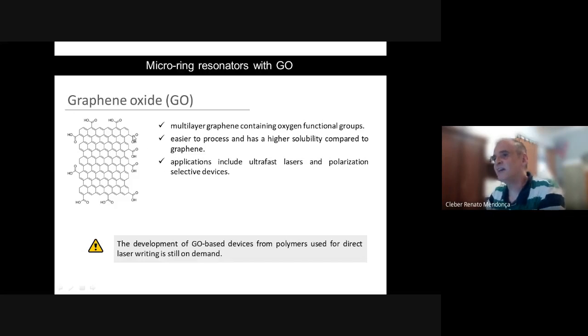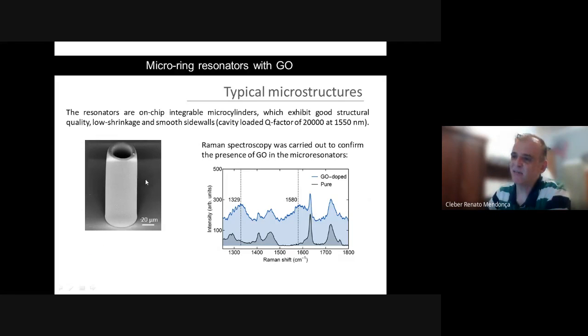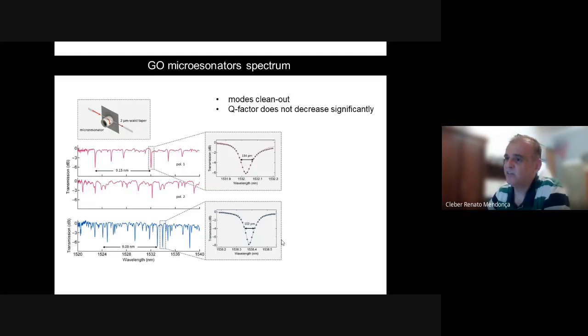We have also been able to incorporate graphene oxide in those microresonators, and the idea here, of course, was to evaluate the nonlinearities of graphene in these microresonators. So again, a microresonator, we incorporate graphene. Here will be the pure resonator, and when we have graphene, we have a higher Raman spectrum, just to prove that we do have the graphene in our resonators.